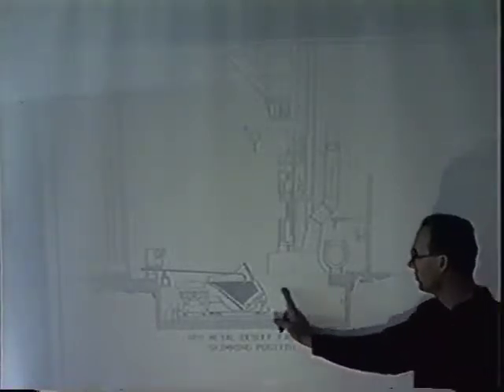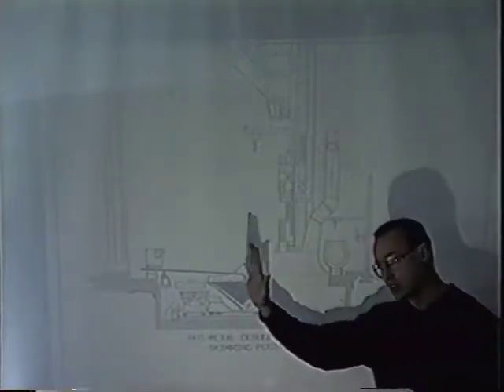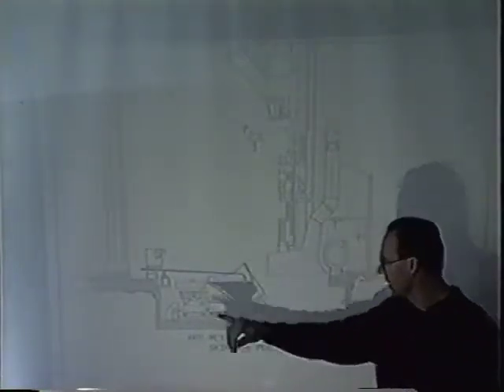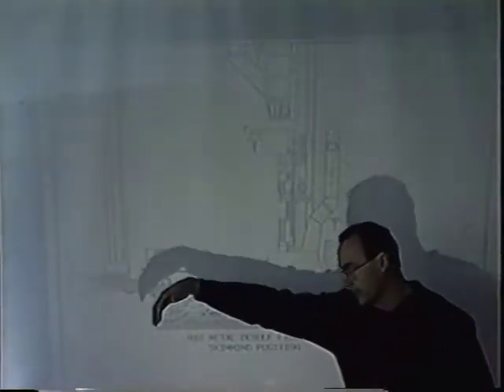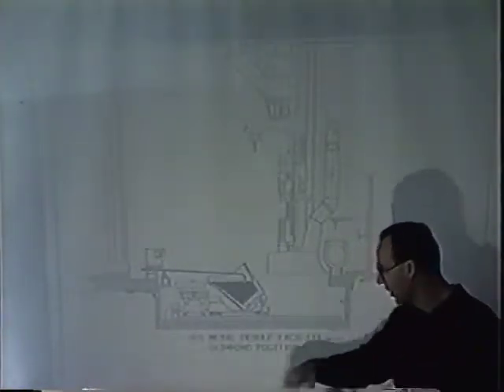So now we got to get that slag off of the ladle. It's kind of a crude process, but what we do is we bring the ladle out this way, tilt the ladle, and the slag is now sitting on top, and we take a rake, and we literally rake all that slag off into a slag pot. And hopefully get rid of the sulfur in the process. And here's a fairly decent picture. You can see the slag. The slag is the dark area right here. The hot metal is the bright stuff in the back. And this is our rake, raking the slag off the top of the ladle. We do lose some iron when we do this.